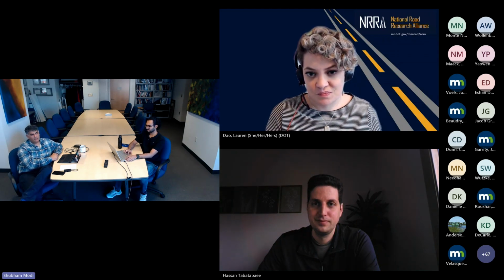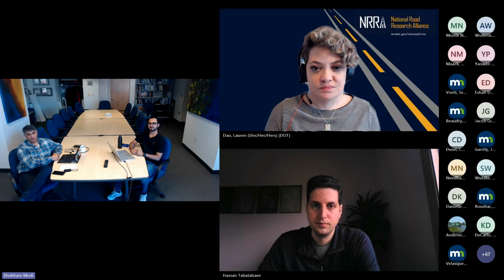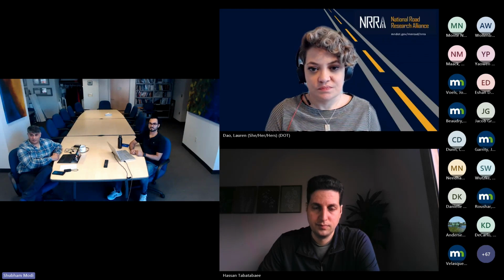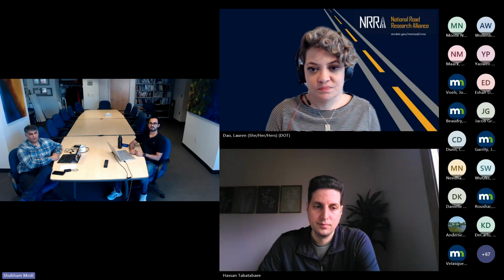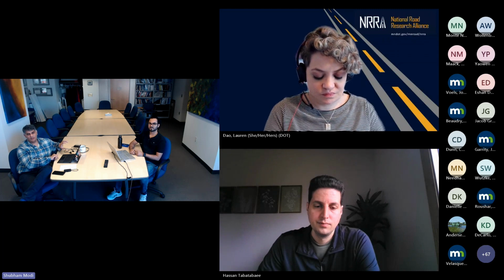Yeah, thank you, Rahul, for those questions, and they are very good questions. I will first say that in the first round of testing, we did use very heavy-duty analytical methods to evaluate these materials, especially the binders, using a lot of chemical and physicochemical testing. The practicality here is relative. We are still talking about laboratory mixture performance tests. It's not at the level where you would use this for process control or a QA type of practicality. We are going from something like 3 to 4 months of testing needed to make sure that you are okay with a certain crude source,